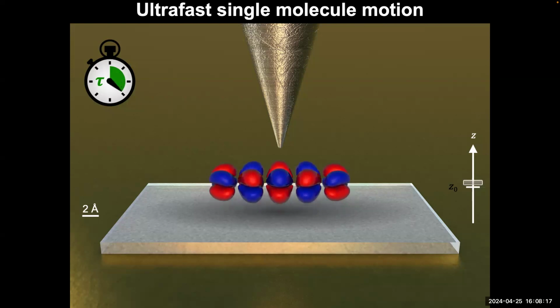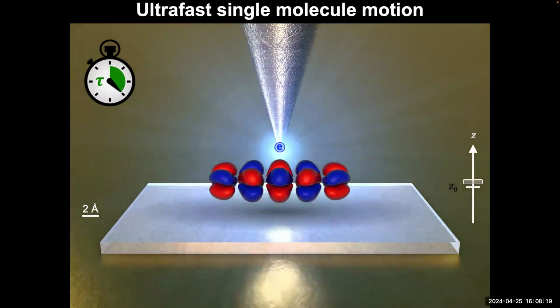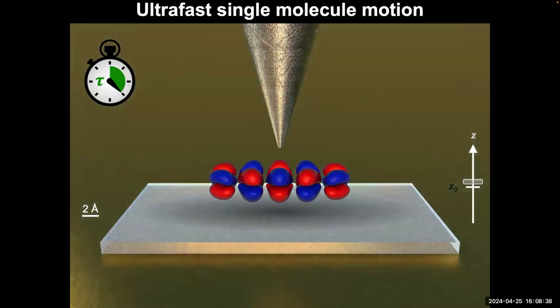Now, the interesting thing was when we came with another terahertz pulse sometime later and removed another electron, our probability of taking it out of that molecular orbital depended on the elapsed time tau because the gap width was oscillating. So remember, if we move by an angstrom, the tip height, it changes by an order of magnitude. So this molecule is moving up and down, oscillating and changing the tunneling probability as a function of time.